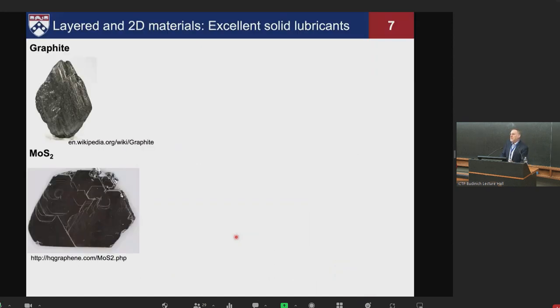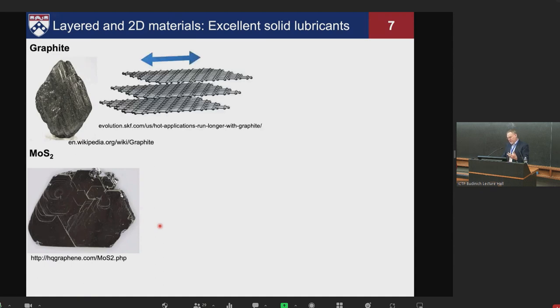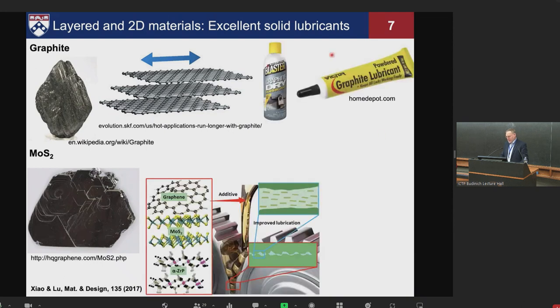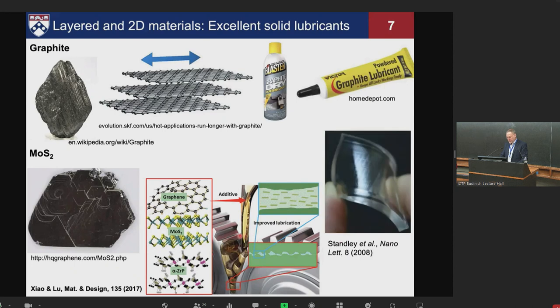And this is what we've been focusing on over the past several years, our 2D materials and layered materials. I think this audience needs no introduction to the importance of these, which come in bulk form, thin film form, and monolayer form. The easy shear between the layers, of course, leads to low friction, and this has allowed them to be incredibly successful as solid lubricants. You can buy them to put on dry, you can grow them as thin films, you can spray them on a surface in a suspension, you can make them additives as particles inside of lubricants, and they can help to reduce friction and prevent wear.